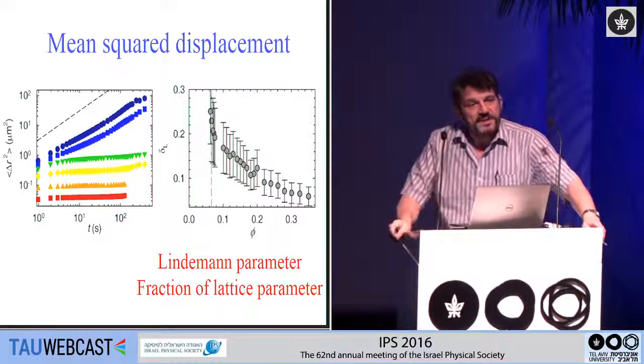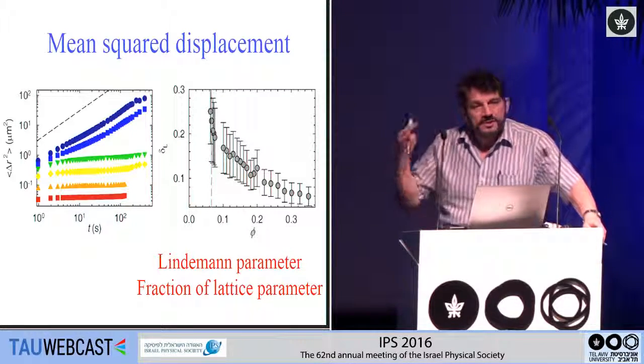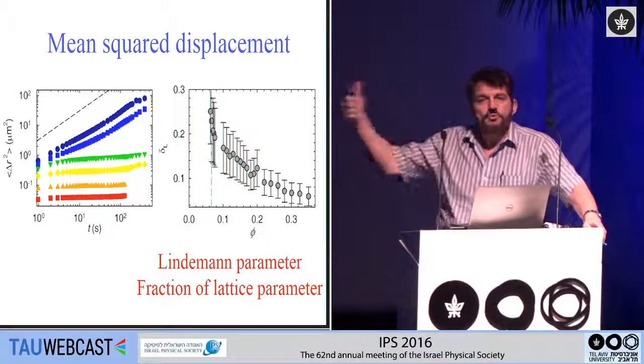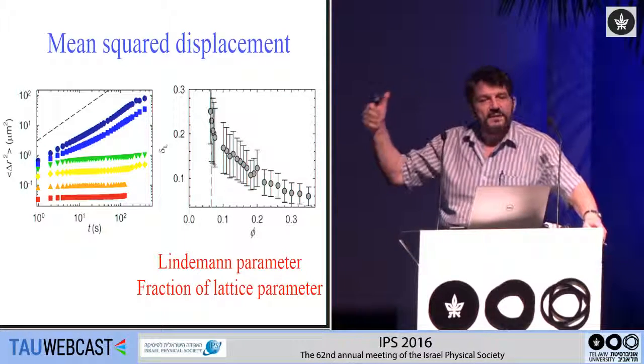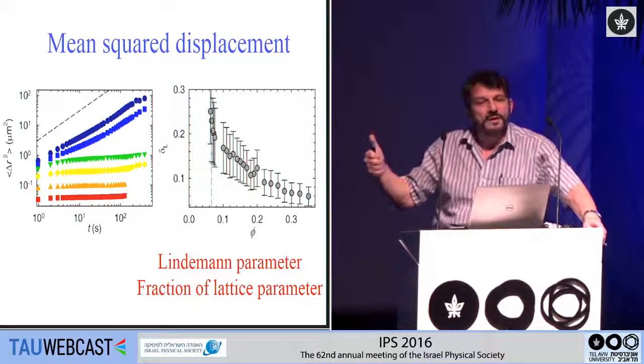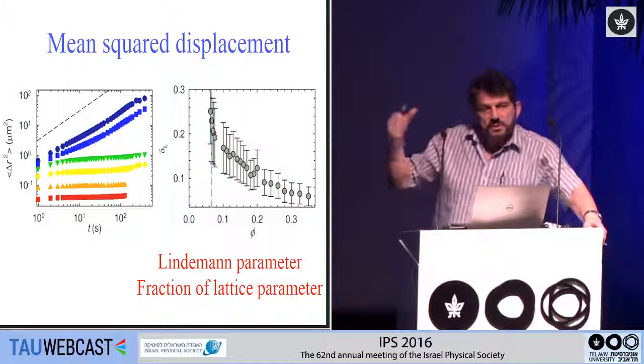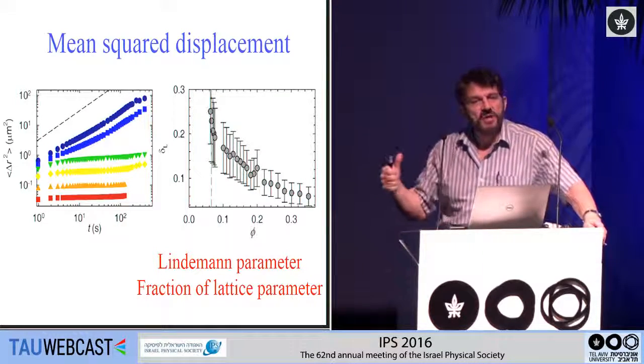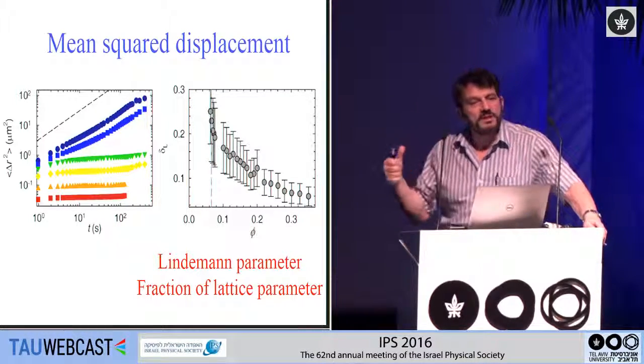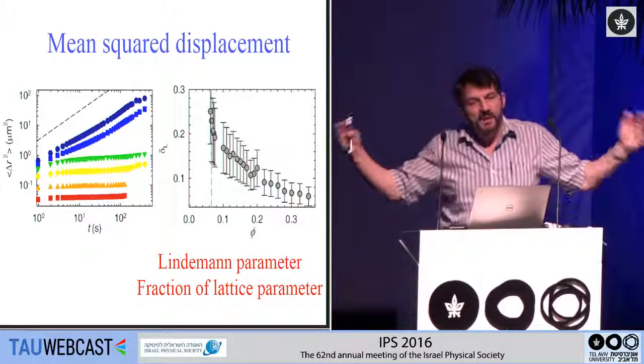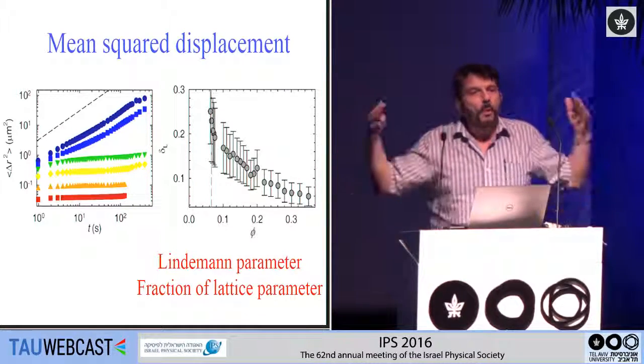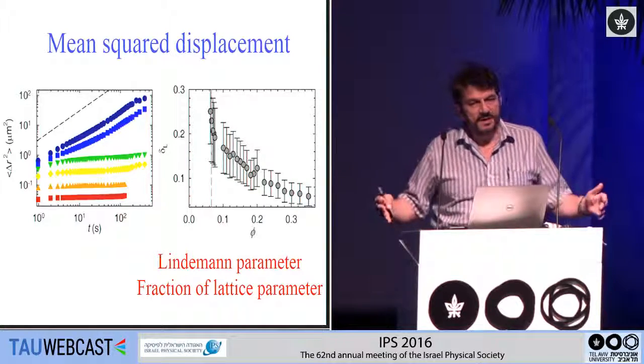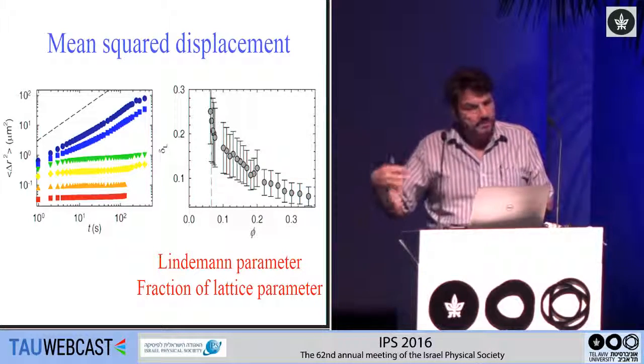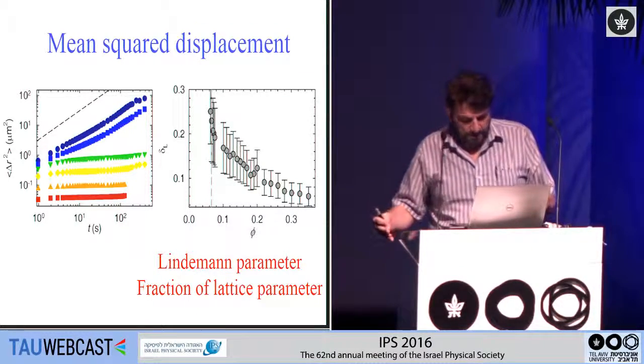What's surprising about this is that if you look in the literature, the Lindemann criterion, the standard rule of thumb, is that when the Lindemann criterion is 0.1, the system melts. So here we see much, much larger fluctuations than in most solid materials, because you're getting much, much closer to the melting point while it's still remaining crystalline. And so the Lindemann parameter becomes much, much larger.